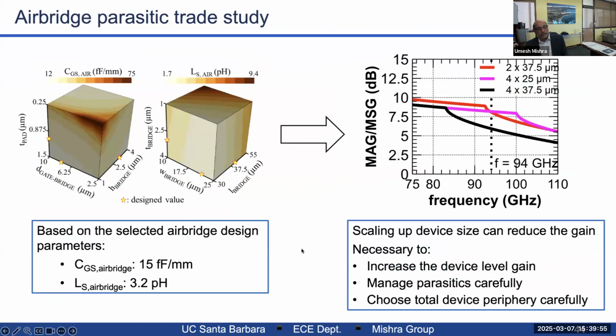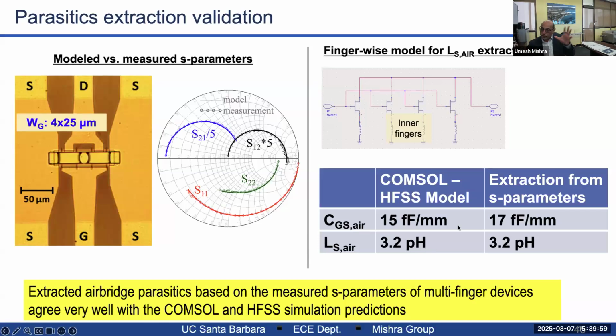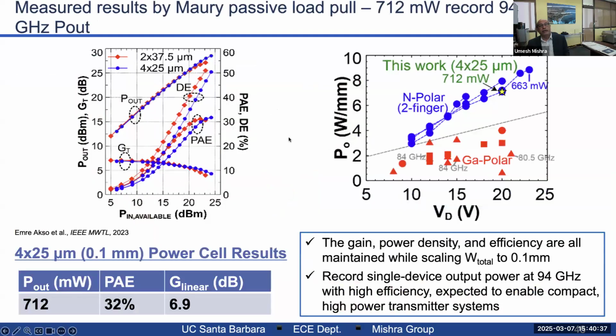We did a big study, but the most important thing I want to tell you is what we found after doing these models and implementing them in the device. What we modeled for the air capacitance of the air bridge was about 15 femtofarads per millimeter. What we got was 17 femtofarads per millimeter. And what we modeled by HFSS was 3.2 picohenries, and we got exactly 3.2 picohenries when we built the device. So the models were correct, the implementation was correct, and we ended up getting excellent devices. We got a single device at 94 gigahertz giving you 712 milliwatts with 32% power added efficiency and 7 dB of linear gain. This is really, truly exceptional.